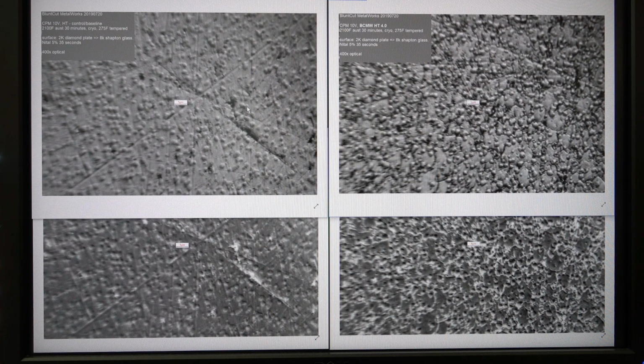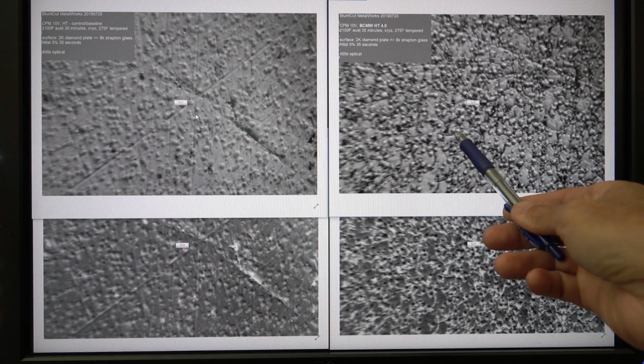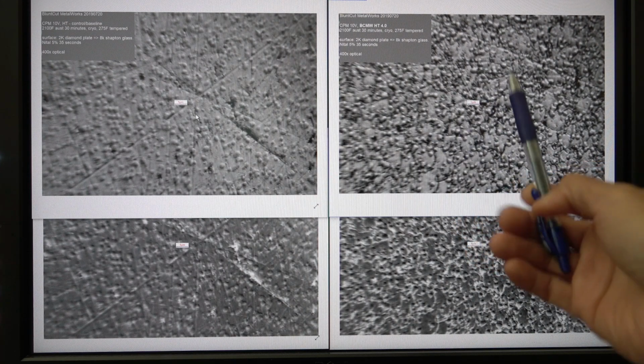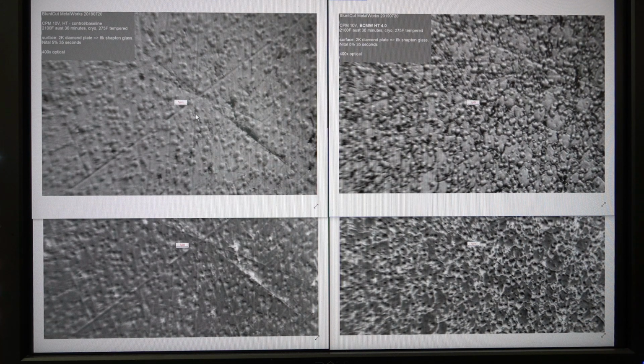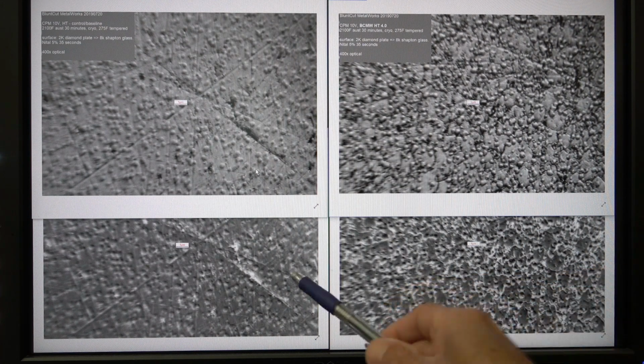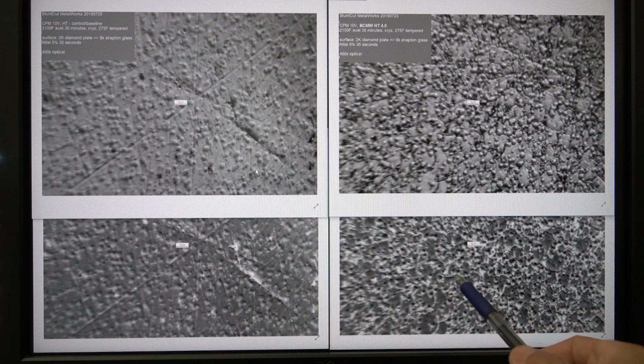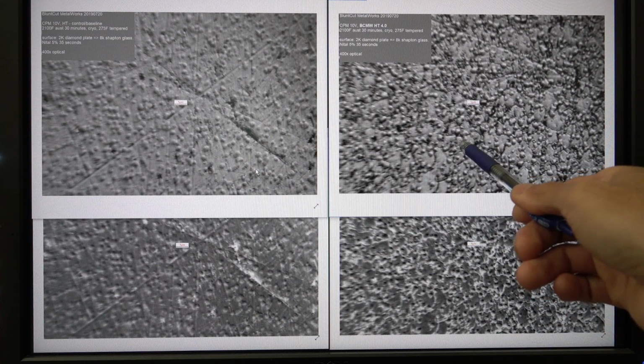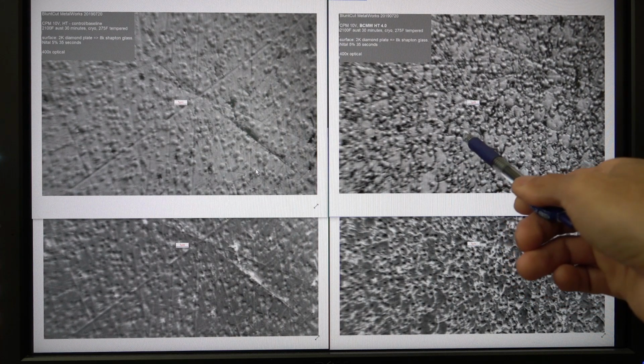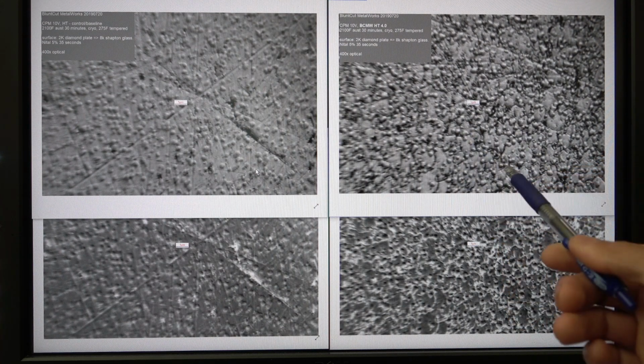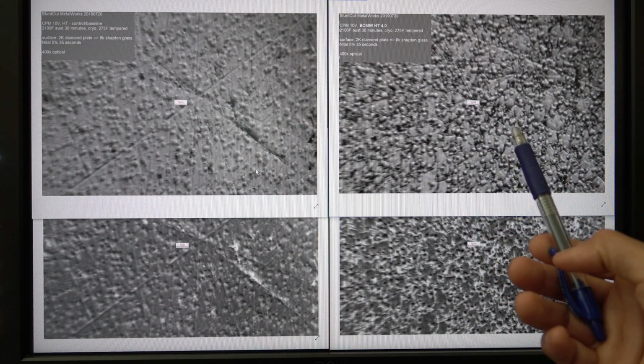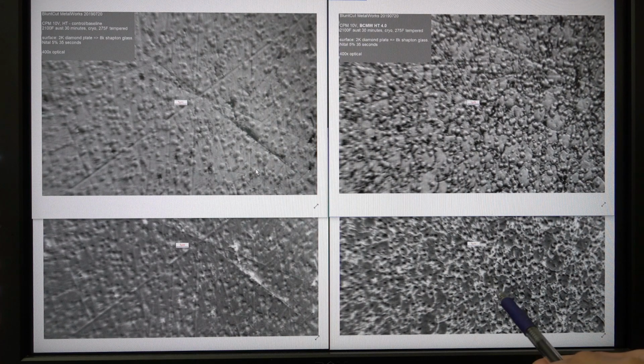And if we're counting, this is going to have a higher population of carbide than this one. This one will have higher. See if this bump is a lot taller bump. And if you go to the inverted picture down below, when this pit or crater and this one, you can see this one is much deeper. That means the matrix is a lot stronger holding on to the carbide. So they allow the carbide to protrude away from the surface a lot more.